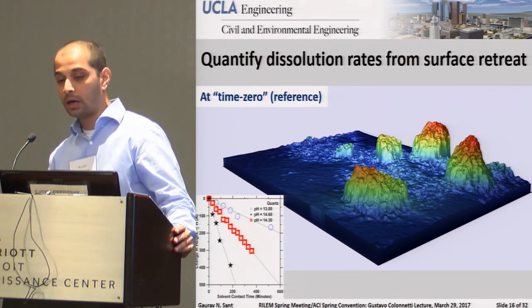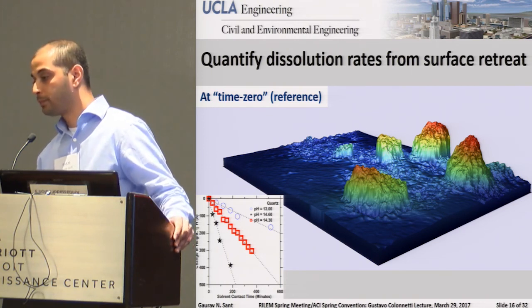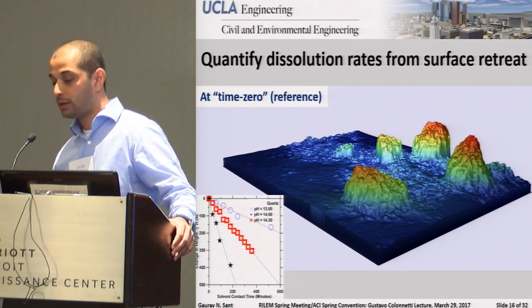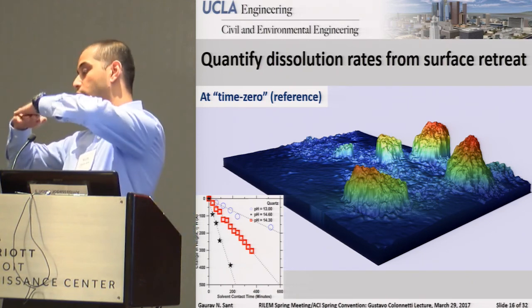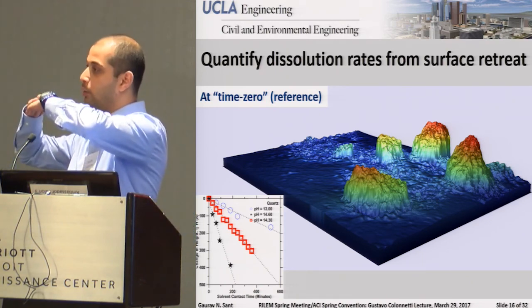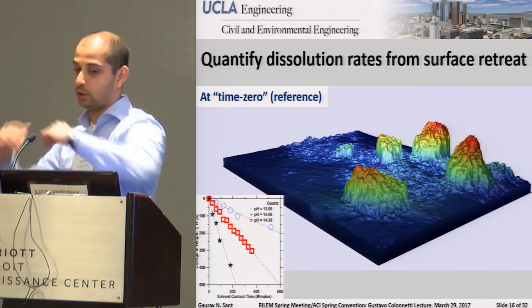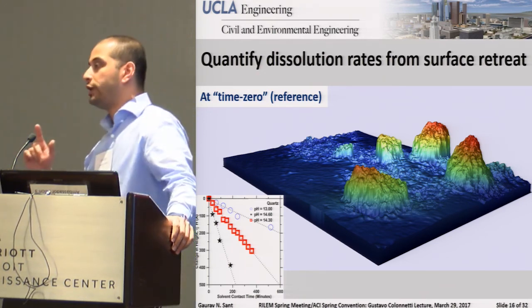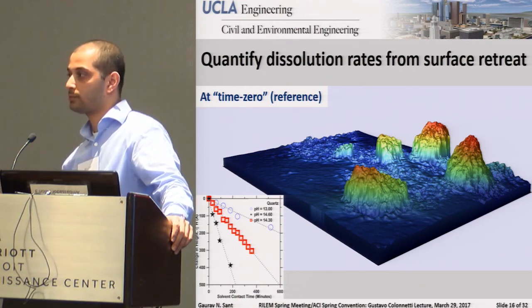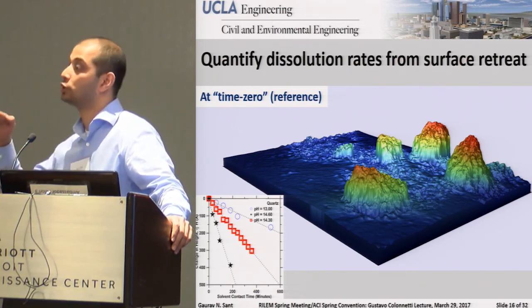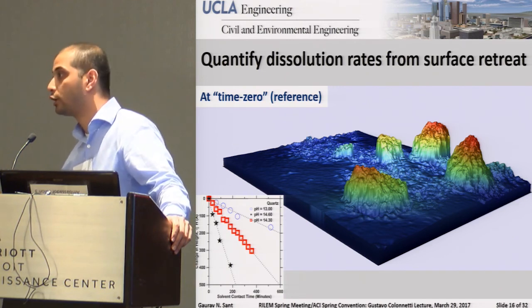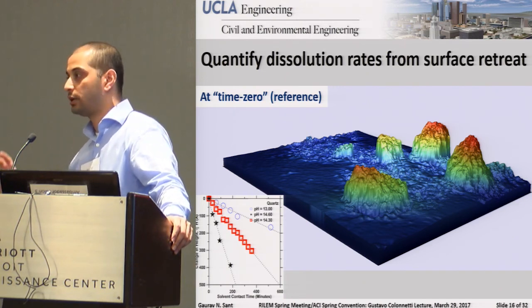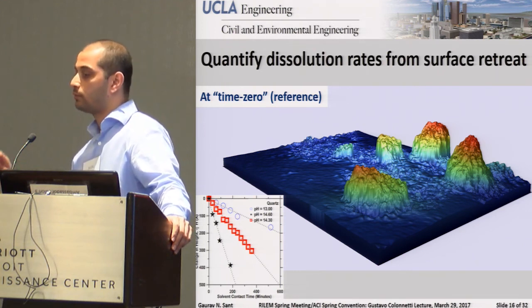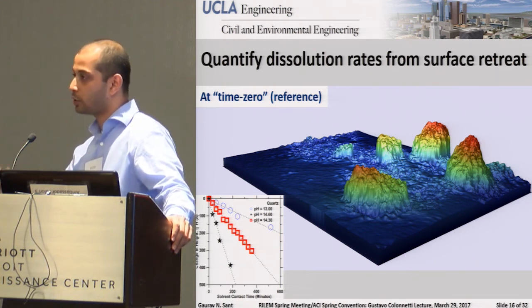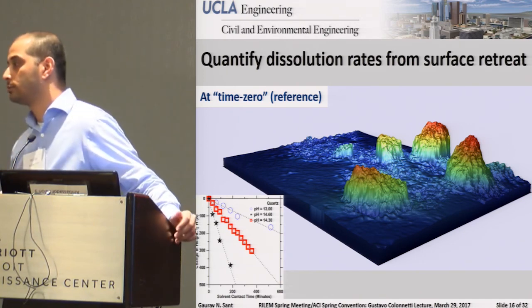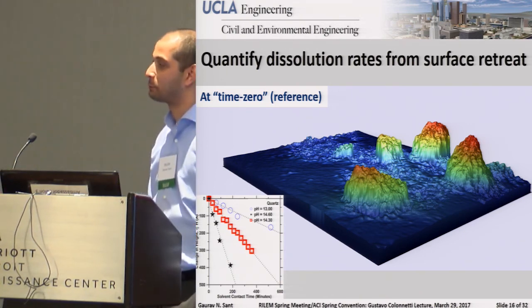As an example, there are a couple of problems with it. When you're doing interferometry under immersion, imagine you've got a surface, a thin liquid film, a glass optical window, and then the objective, which is looking through all of this. The compensation needs to be dynamic, because it needs to account for changes in temperature and for changes in concentration in the solution as it dissolves. Because as the refractive index changes, you need to compensate for it. So it turns out to be quite a mess. It is in fact easier to develop a system for repositioning accurately once you remove the sample than doing glass compensation. So we abandoned glass compensation some time back.